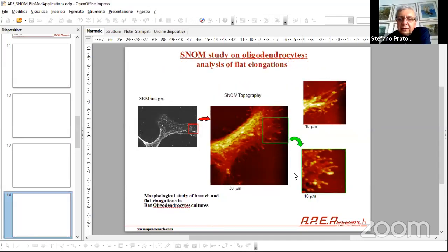So this is a topography. This is exactly what you can obtain also with AFM. This image is 30 by 30 micron, and you can zoom in with the AFM. So this is what you can get with AFM. You see very, very small structures here. Those are 10 nanometers in height.